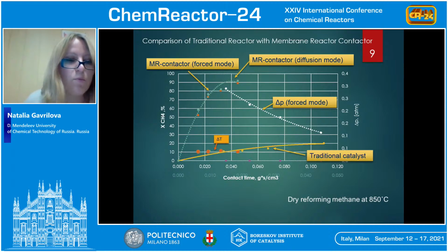We also compared two modes of the contactor with diffusion and forced transport. As you can see in this graph, regardless of the reagent transport mode, characterized by pressure drop at the reactor inlet, the methane conversion rates are close. Since dry reforming of methane is an endothermic process, the temperature of the gas medium on both sides of the membrane catalyst was monitored during all experiments. As you can see on this graph, these temperatures were different. The temperature inside the membrane catalyst was lower than in the annular space of the reactor.